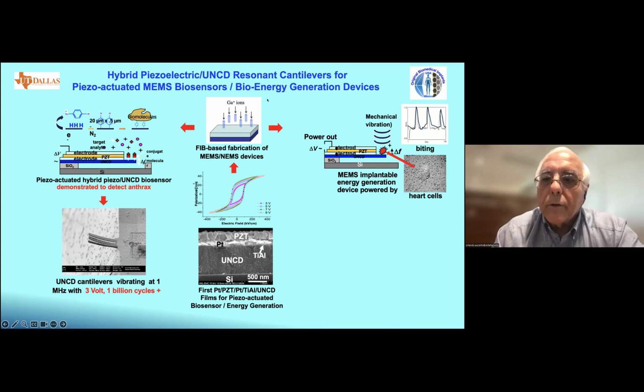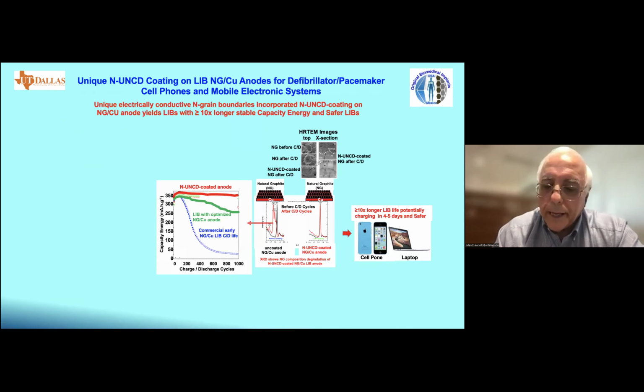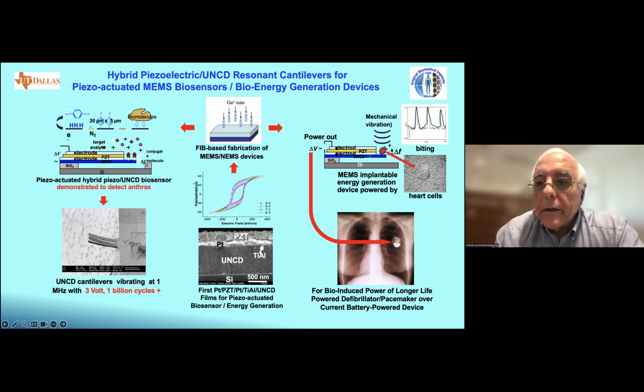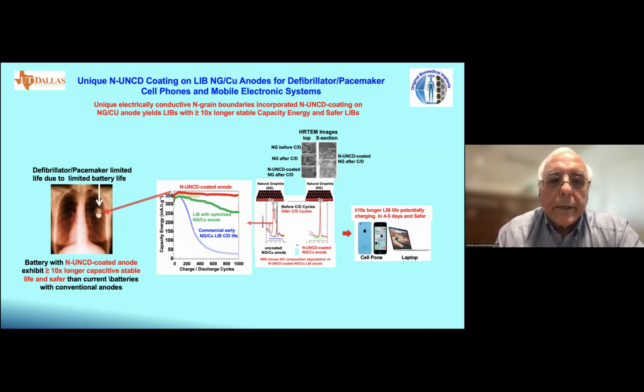The piezoelectric thin films also have the property that if you move this mechanically, you can get electrical current from the bottom and top electrodes. So what we did here, we put a cell of a mouse heart, and demonstrated that we can get current out, and we are trying to develop this to power defibrillator pacemakers, because the defibrillator pacemaker today, with graphite on copper electrodes for the batteries, degrades sooner than desirable. And I know that because my wife got a defibrillator pacemaker from Medtronic in 2013. They told us that in 9 to 10 years, they were going to change the whole box. It was only 6 years.